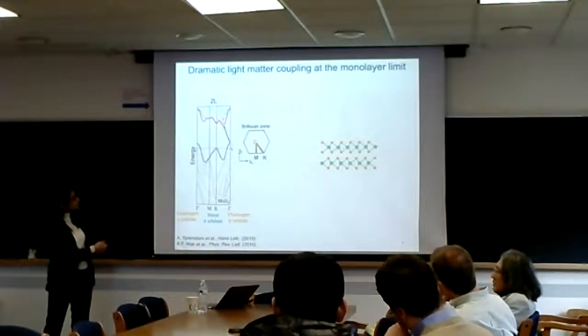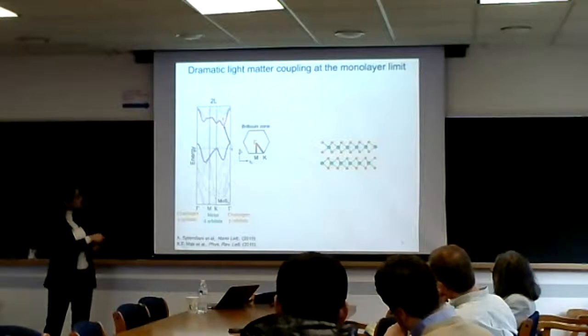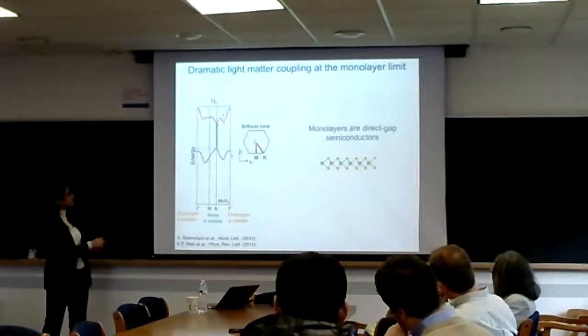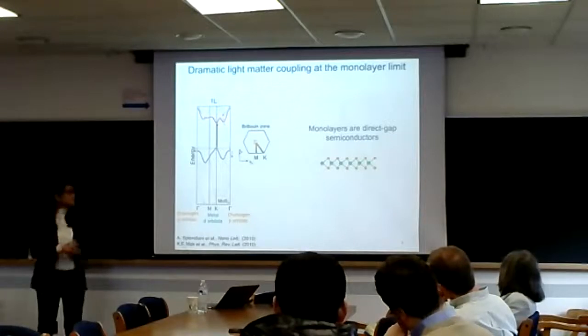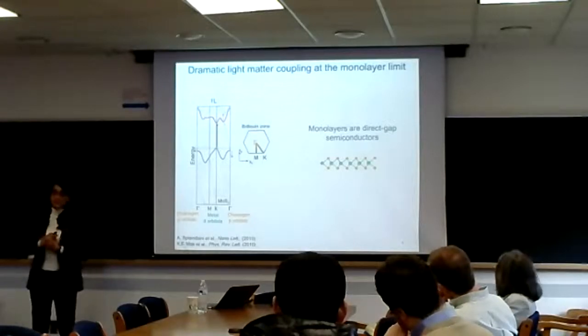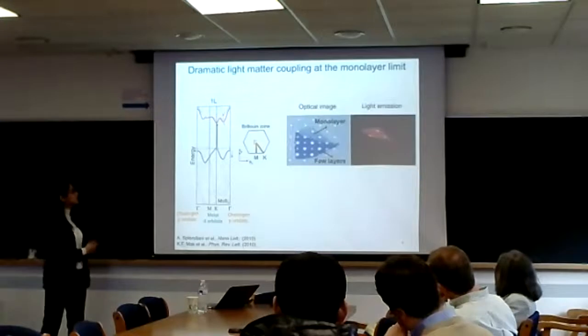So as you thin this material down, you have quantum confinement effects that kick in on the out of plane direction. So this indirect gap, which has contributions from the chalcogen orbital, starts to increase, and at some point becomes larger than the direct gap, and that point is when it becomes atomically thin. So why is a direct gap semiconductor interesting to any of us?